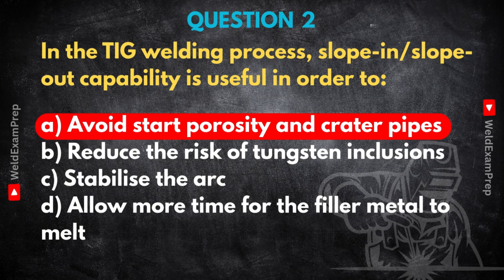And what are the immediate signs an inspector would spot? What's the giveaway? Well, the most obvious sign of insufficient slope out is exactly what we mentioned, the crater pipe. You'll see a distinct concave depression right at the end of the weld bead. Often, you might even see a tiny crack right in the middle of it. In an exam, if you see a picture of that, your first thought should be improper slope out. And long term, that pipe is just asking for trouble. Fatigue cracks love starting there. It's a serious defect, even if it looks small. Got it. Easy to spot, but with serious consequences.